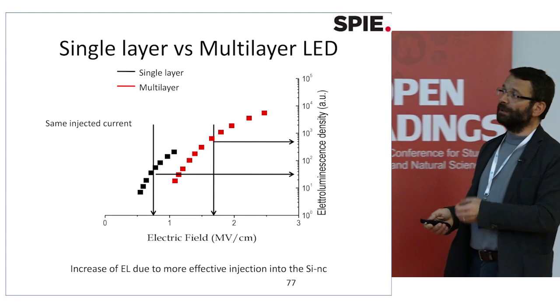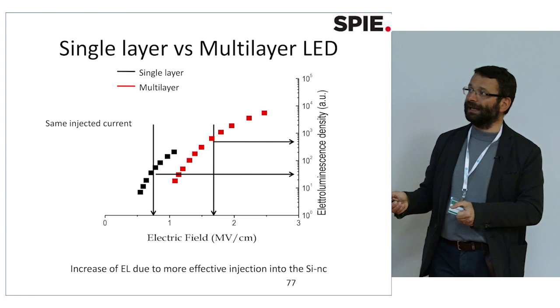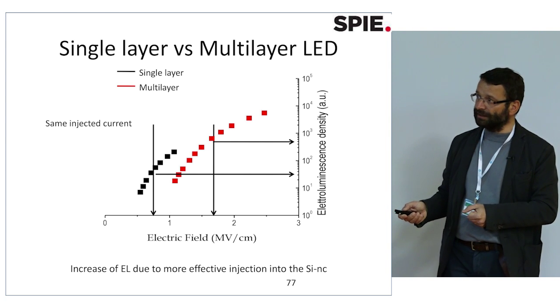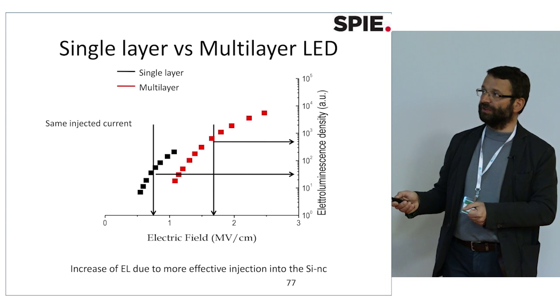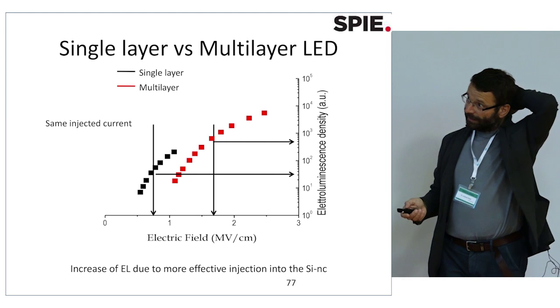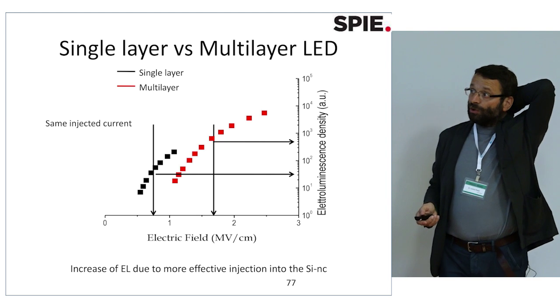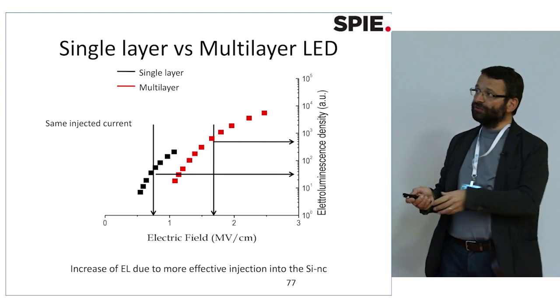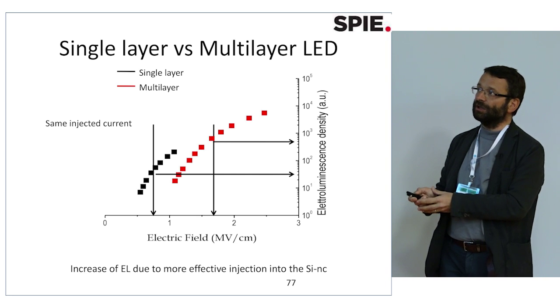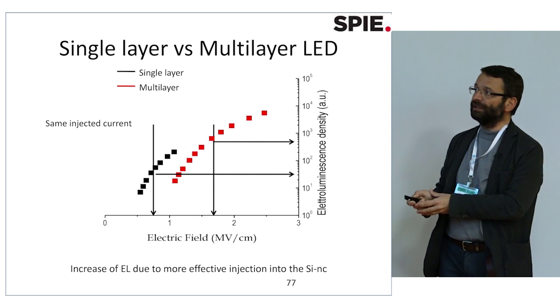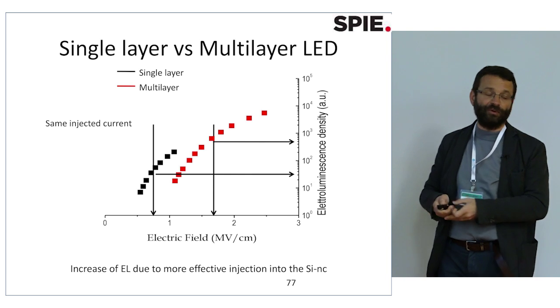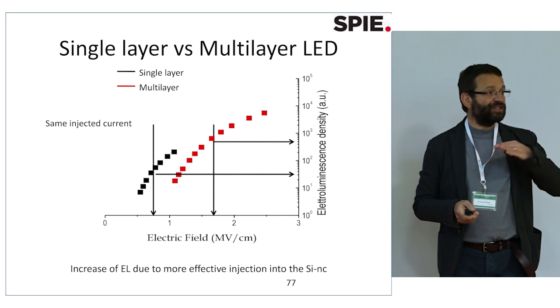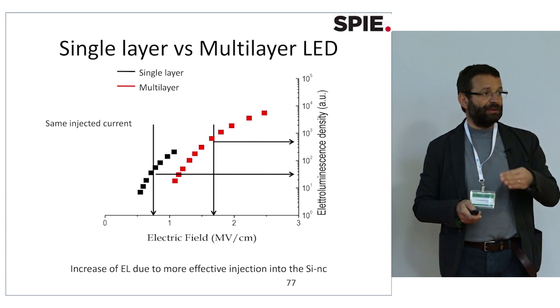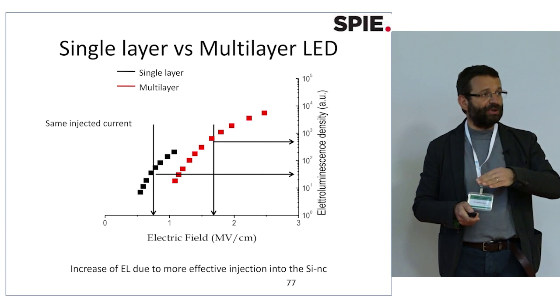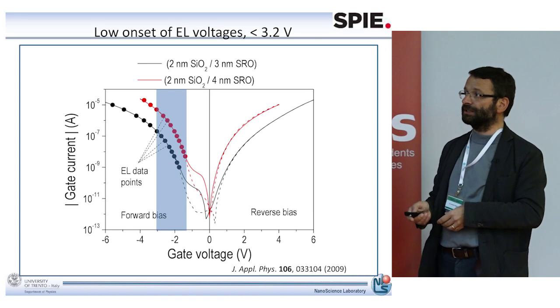So now if we look at the current level, at the electric field value that achieves the same current for the multi-layer as well as the single layer, and then we look at the electroluminescence coming out, we do see that the electroluminescence in the case of the single layer is much smaller than the electroluminescence that we get for the multi-layer at the same injected current density. So that means that in the multilayer, we are able to excite the nanocrystal more efficiently.